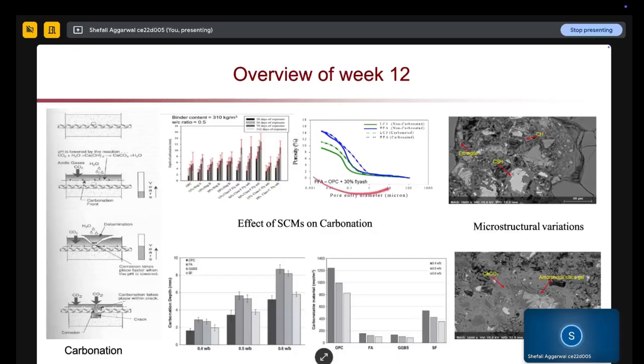Same thing here, it has been done using MIP, that porosity has been checked. So in LC3 system, your porosity initially will be high, but with carbonation, your porosity will increase. Okay, same way for fly ash. In non-carbonated versus carbonated, your porosity is increasing.